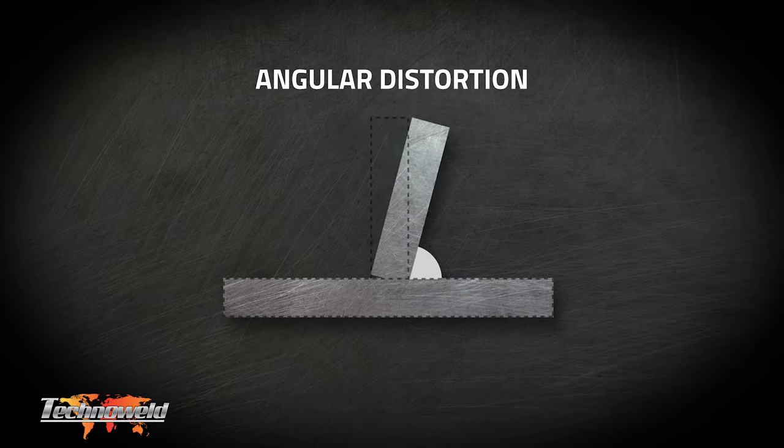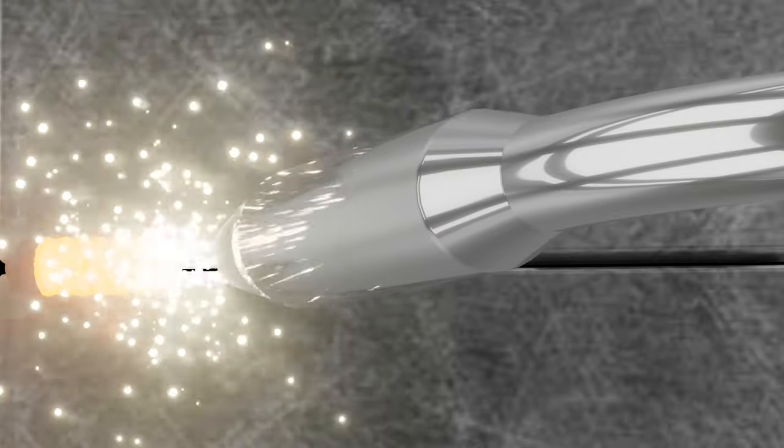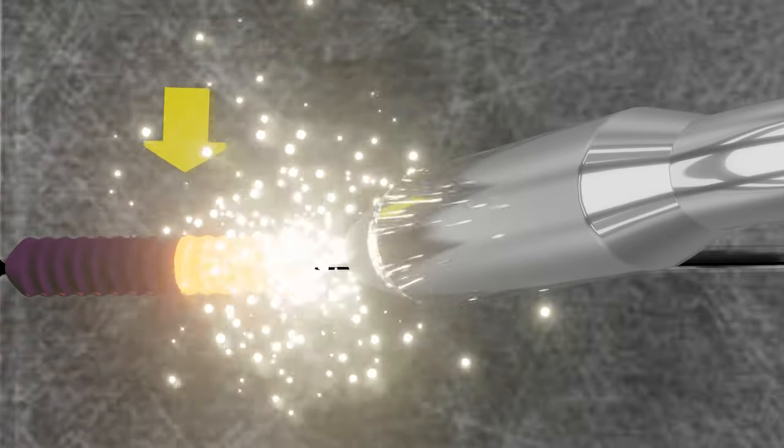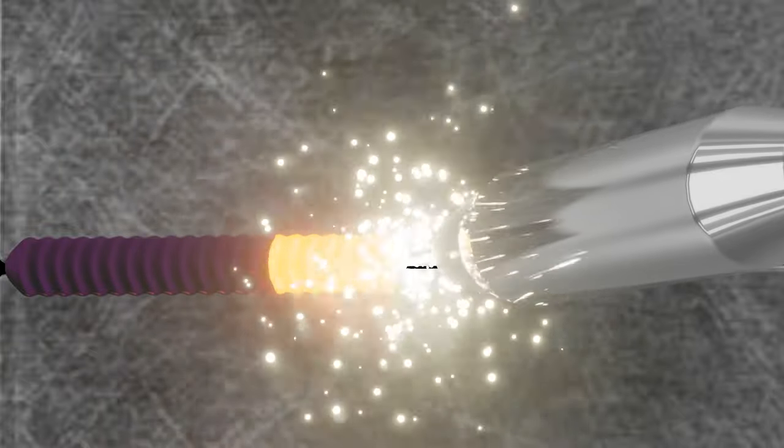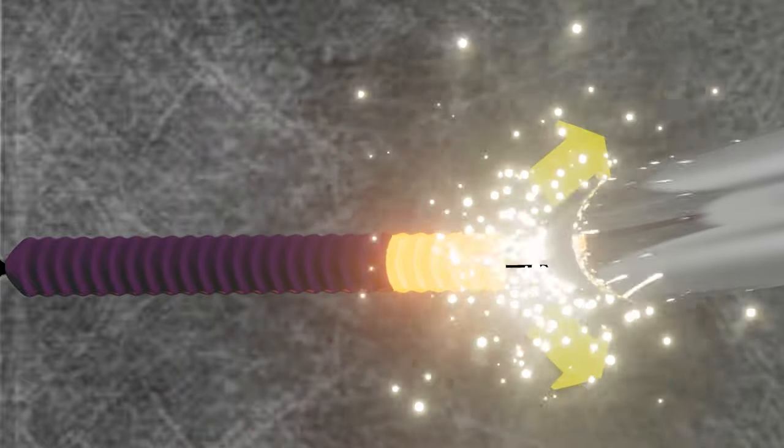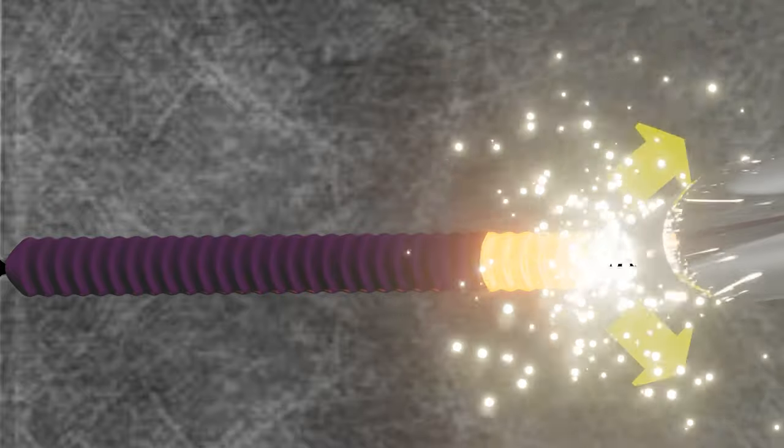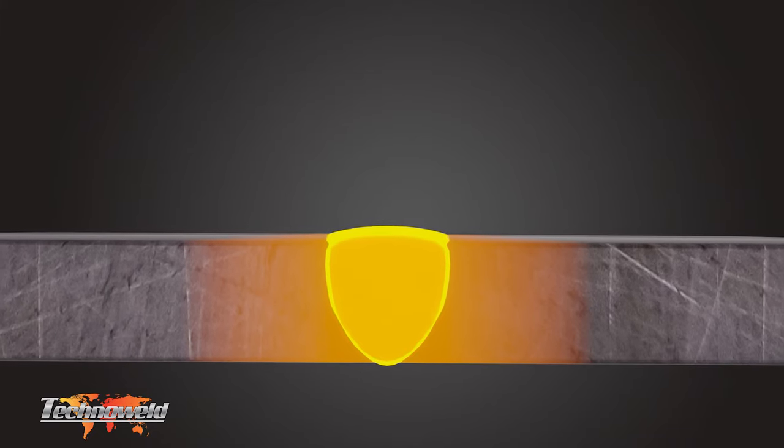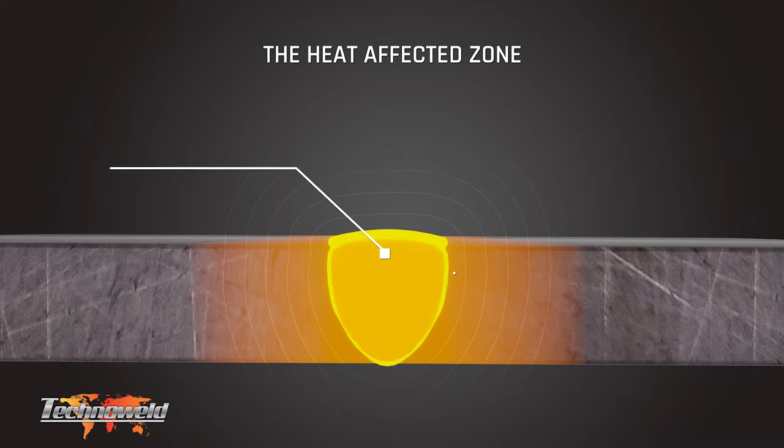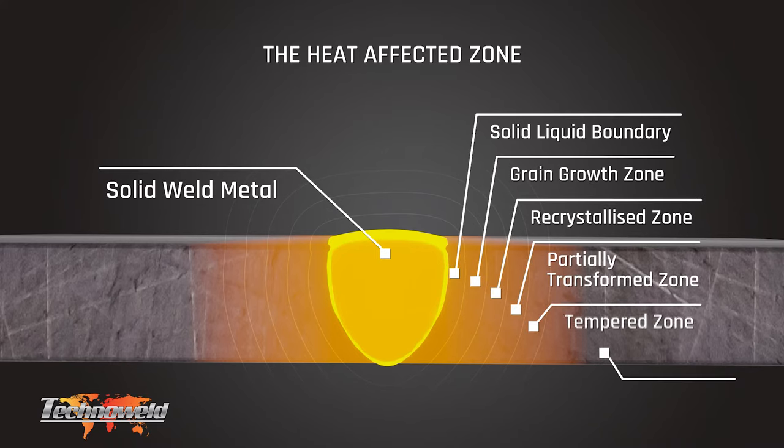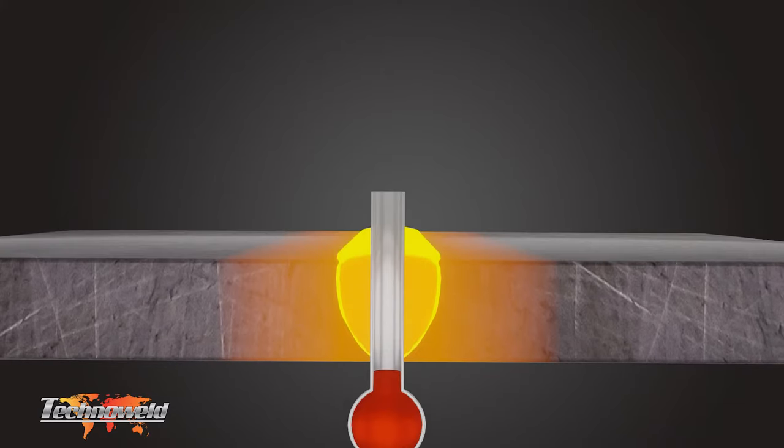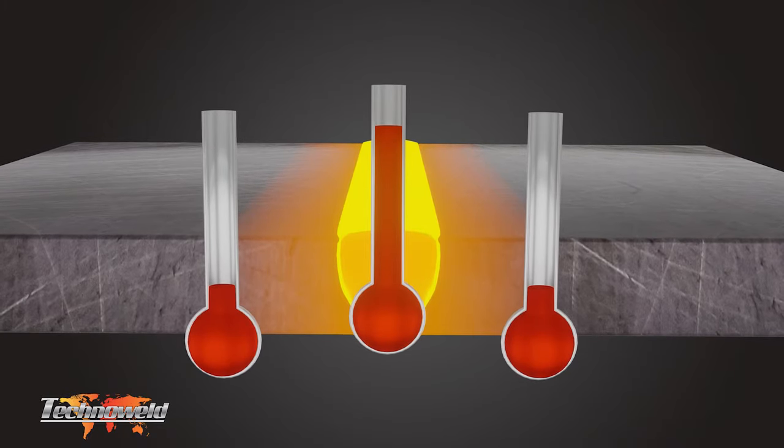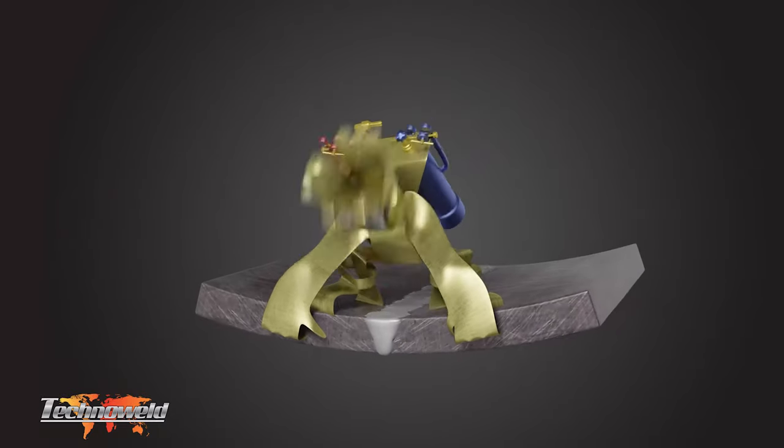Look what happens when we weld two plates together. When thinking about the weld bead, keep the metal bar in the vice in mind as it behaves very similarly to the weld. At and ahead of the arc, the heated weld metal is causing an uneven expansion and contraction of the material surrounding the molten weld metal. The plates are also being heated by the arc with a sharp drop in temperature as the weld solidifies behind the arc. The weld metal cools rapidly causing continual contraction behind the weld pool. This whole area is called the heat affected zone. Larger welding beads increase expansion and contraction forces; the contraction forces following the arc become stronger. It's important to note that as the heated weld bead is cooling and contracting, the heat from the bead is transferring to the plates on either side, increasing their temperature and causing them to expand.